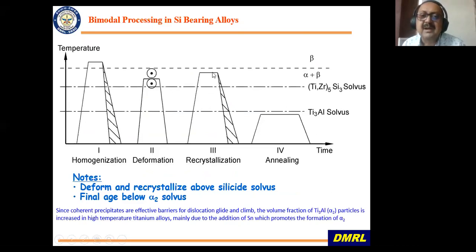these alloys are going to become brittle. And then after the final recrystallization and heat treatment, you finally anneal or age it below the Ti3Al solvus. Ti3Al is an ordered structure, and when it precipitates, deformation gets restricted. You have lower ductility, so you don't want to do any processing after this, but it strengthens. That is why this aging treatment is given to high temperature titanium alloys, to get Ti3Al precipitation, because it renders strength and also gives good creep properties.